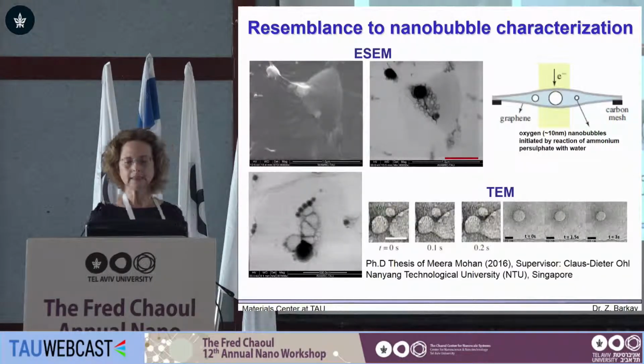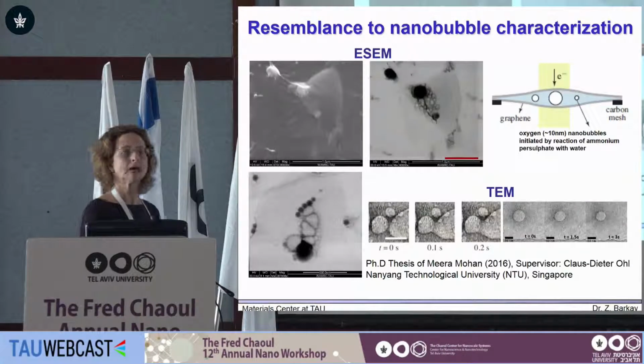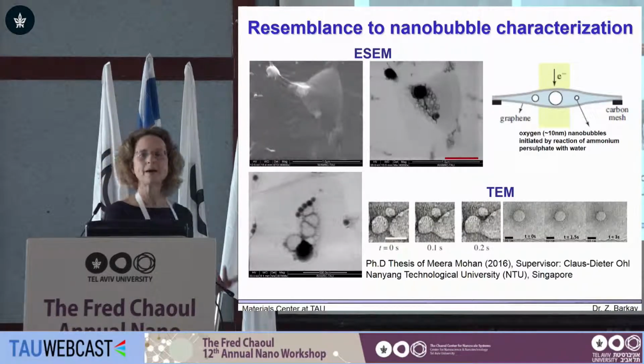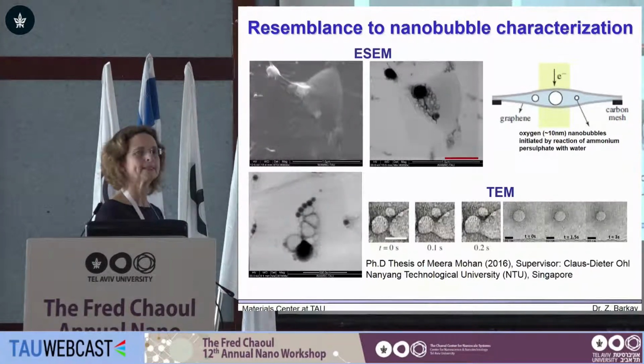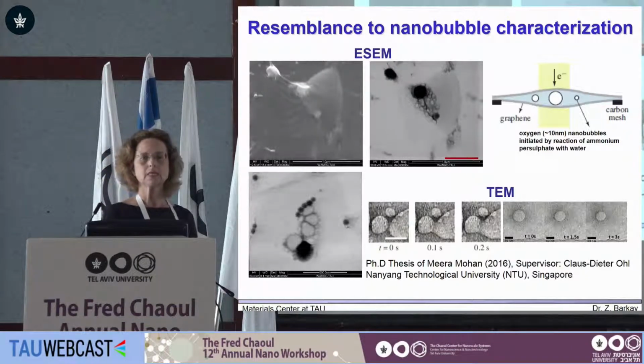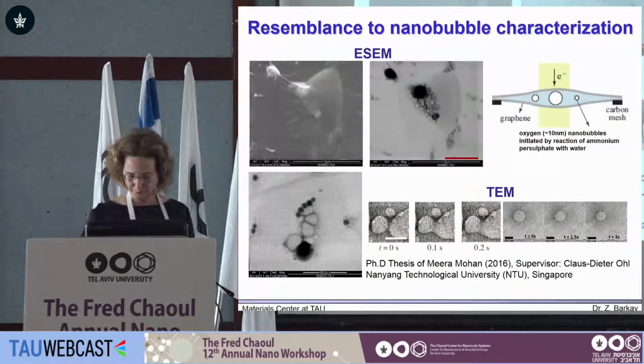In addition, this group was doing TEM measurements, and they found - this is part of the thesis that was done - a coalescence lifetime of sub-seconds. They also followed single bubbles that look spherical in a non-saturated environment, and what they saw was some stability over a time scale of seconds. So in case this issue is really correct, that these are free bubbles, it's a really big story here, and this is still under continuous research.